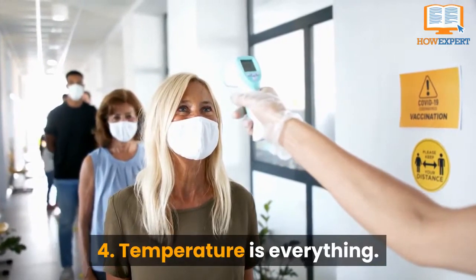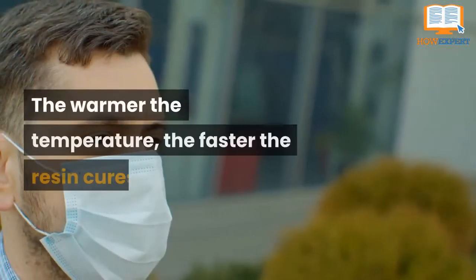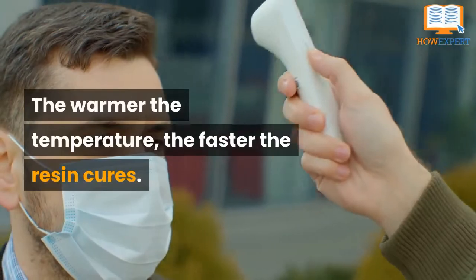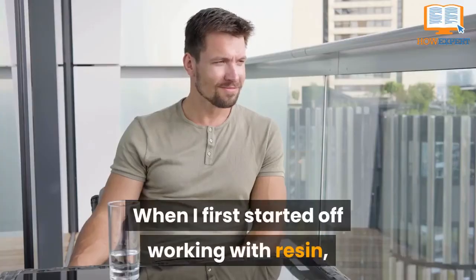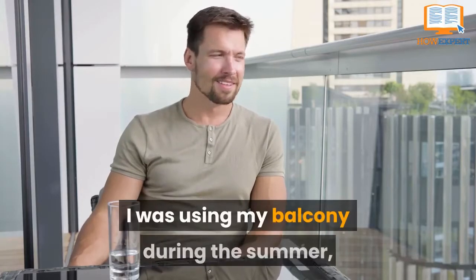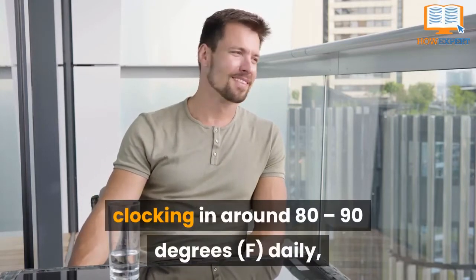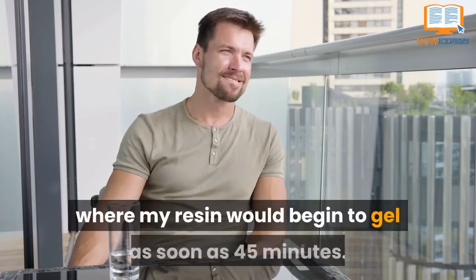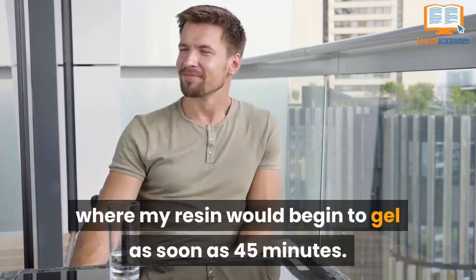Number 4. Temperature is everything. The warmer the temperature, the faster the resin cures. When I first started working with resin, I was using my balcony during the summer, clocking in around 80 to 90 degrees Fahrenheit daily, where my resin would begin to gel as soon as 45 minutes.